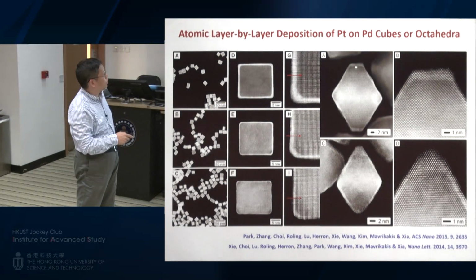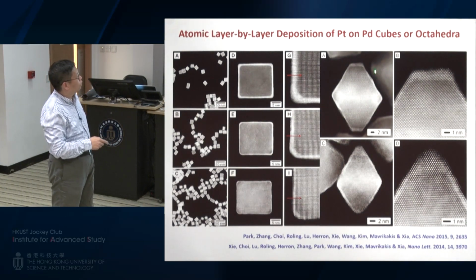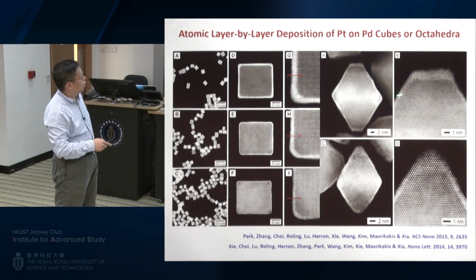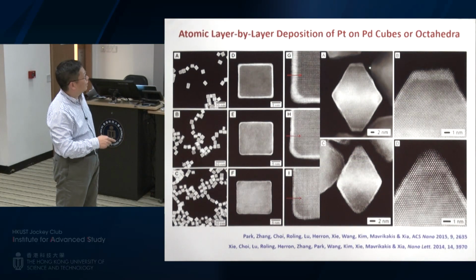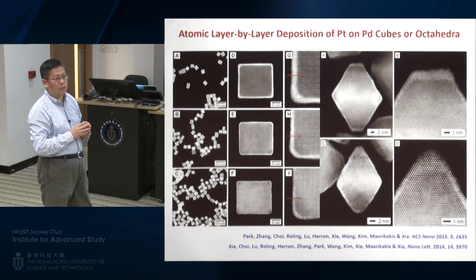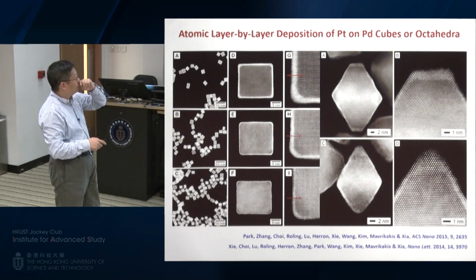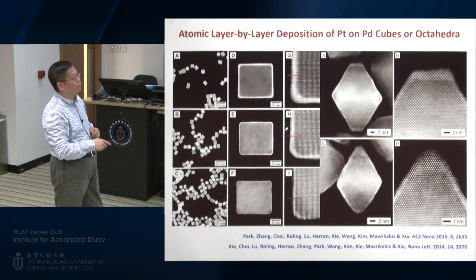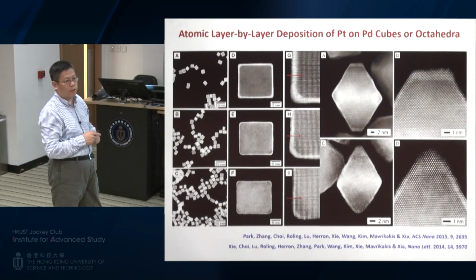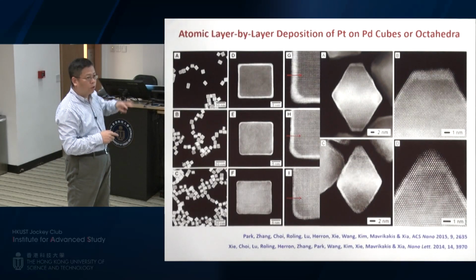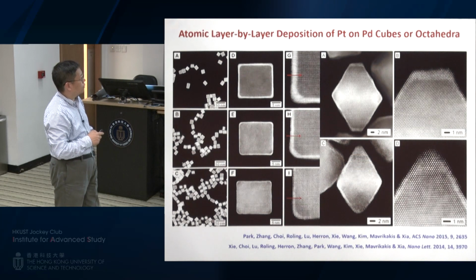So for example, if you switch to octahedron, you can also make similar core shell structures. But in this case, the surface will be different. It's going to be the 111 facet. As I'm going to show you later, this facet is actually better than the 100 facet for oxygen reduction reaction, okay? So you have a way to control the surface structure.